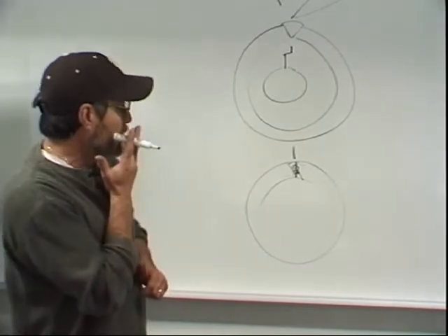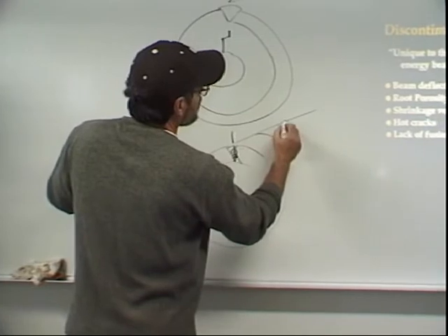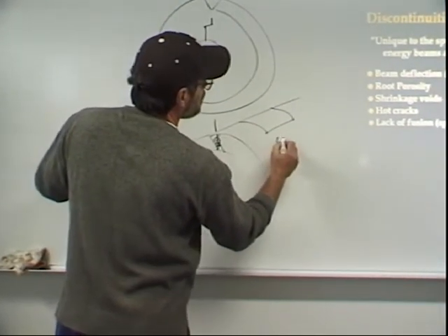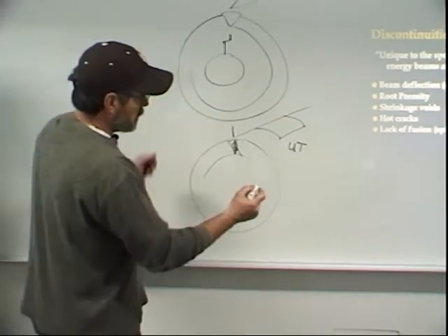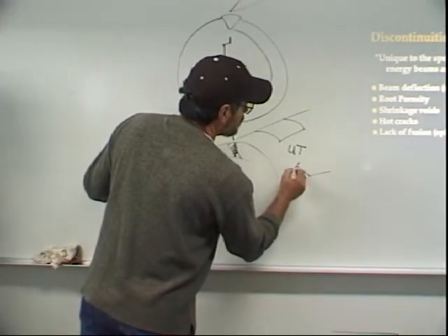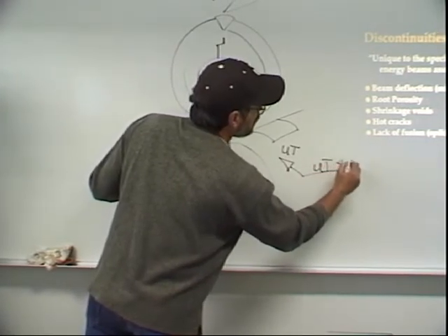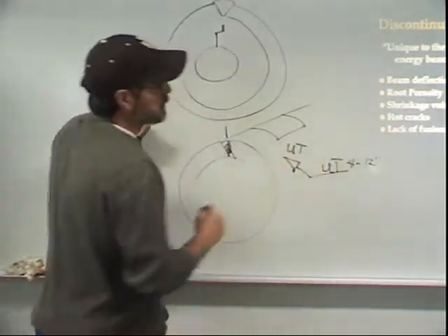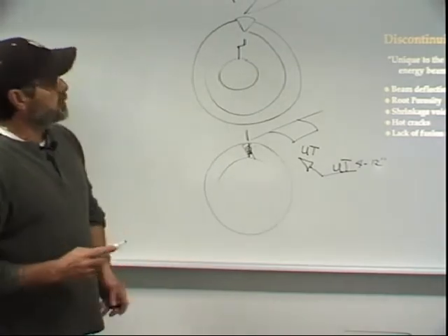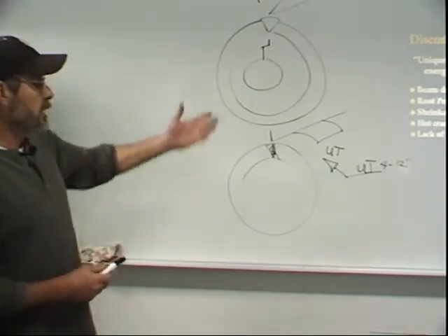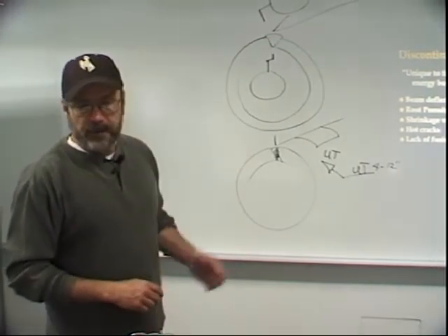And he proved this in court, and what they should have done was, as we've talked about before, they probably should have done non-destructive testing through UT. UT would have caught that in a heartbeat, and of course they would have written that up in their inspection symbol, like so, UT 4 places, 12 inches, and they would have spot checked that, and they would have found out that they were having problems through misalignment. So that was just a lapse in quality control. But that's the kind of stuff that can happen out there in the field.